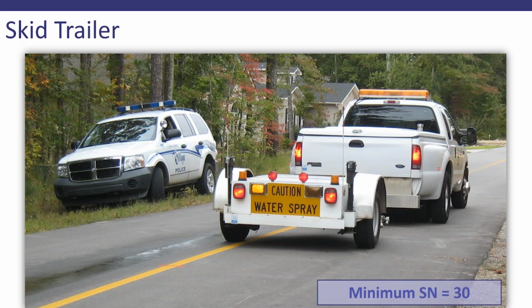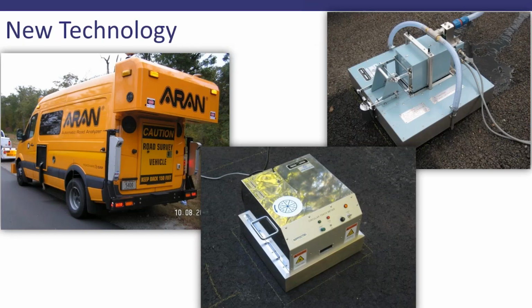There are some fancier ways to measure skid resistance. RDOT has a skid trailer. They spray water and then they'll lock up the brakes at a certain speed and see how much they skid, and that provides a skid number. And I believe typically the minimum skid number that's allowed is 30. Anything above that is good. In addition to that, that automatic road analyzer, that van, again, very expensive, but this is one of the measures that it can provide while it's doing its run, in addition to the cracks and the rut measurements and so on.